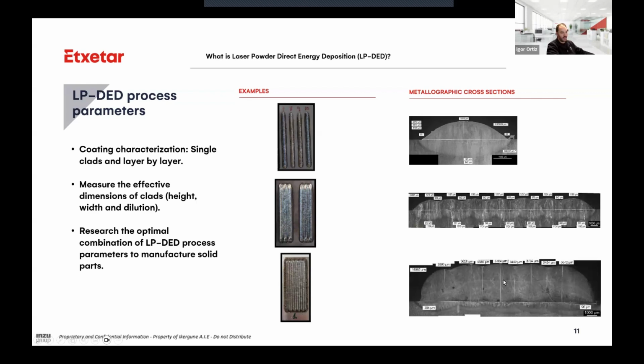5 layers prism or near net shape geometry, and we also check the dilution, the porosity, lack of fusion, cracks, and any issues that we can have in the one layer coating, the prism, or several layer coatings. When we have checked the quality of the substrate with the powder in these three cases, we have a process recipe, and we save this process recipe internally and also to our laser software for toolpath programming.